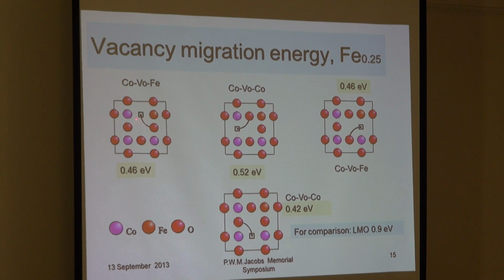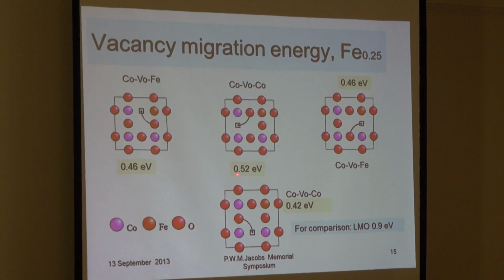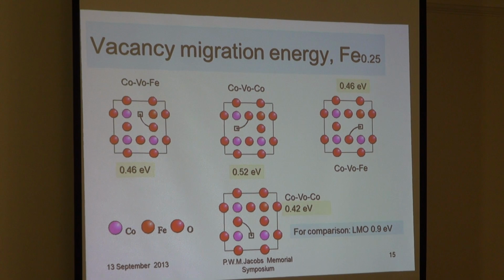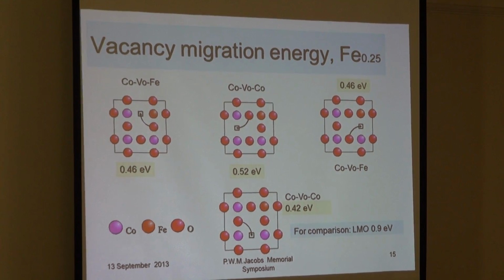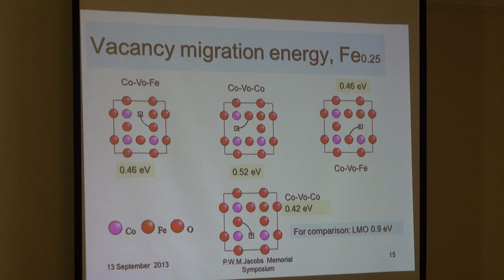And we discovered this problem again when we started calculations of perovskite, potassium niobate, in '92 or something like this. So okay, at any rate, if you calculate all these migration energies, you come to the conclusion that average migration energies could be something like half an eV. And for comparison, essentially all other perovskites, strontium titanate, lanthanum manganite, all these materials give you almost twice higher migration energy. So BSCF is an exceptional material with very low migration energies,